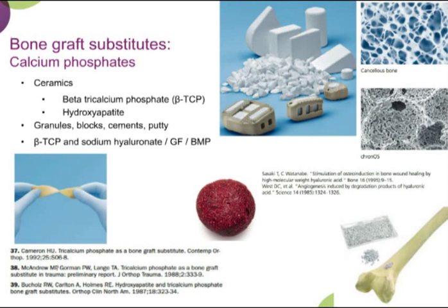The question is whether pore size is a determinant of incorporation, or whether it's actually the interconnecting factor between pores. It's thought that the interconnecting factor, where these little holes are, improves the oxygen tension within the tissue, the graft, and therefore prevents blind alleys from forming in the beta TCP, therefore improving bone incorporation.